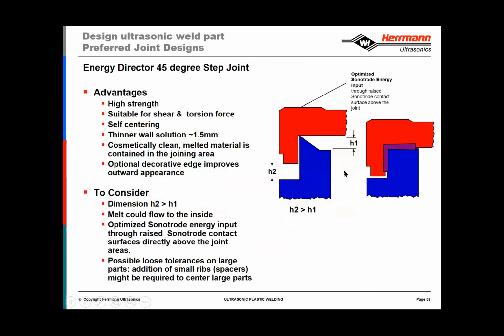This is a variation on that step joint. Again, if you have very thin walls, it's okay to somewhat modify the shape of the energy director, again keeping it pushed over to an adjacent wall so that the melt is contained. And again, just pay particular attention to leaving a bit of a gap between the parts so that they don't bottom out, or that these two surfaces do not come in contact. The welder should control any gap that's left over.